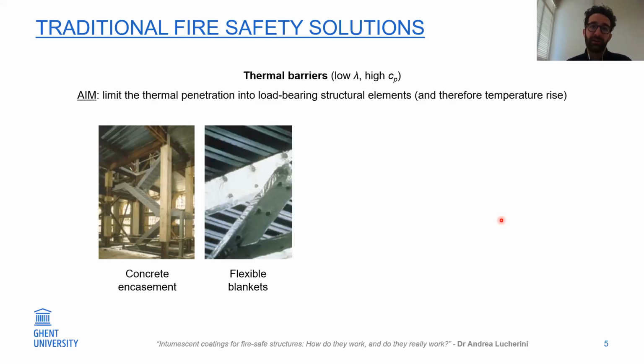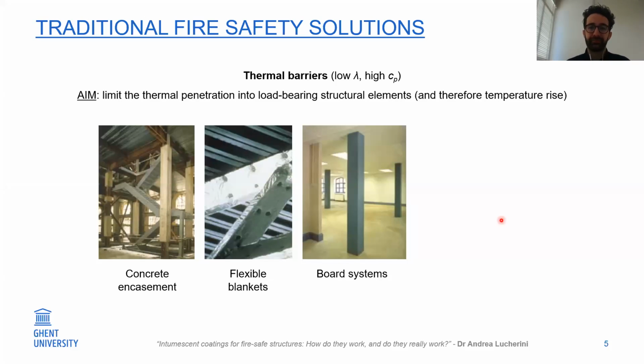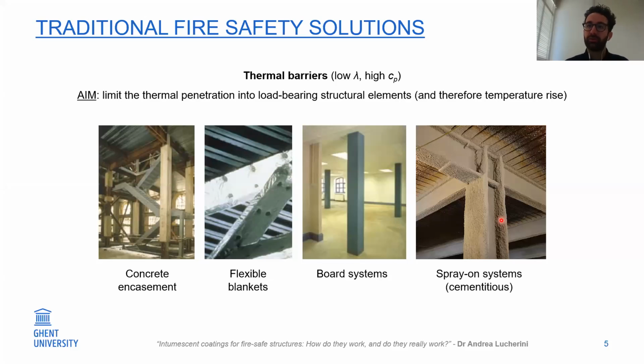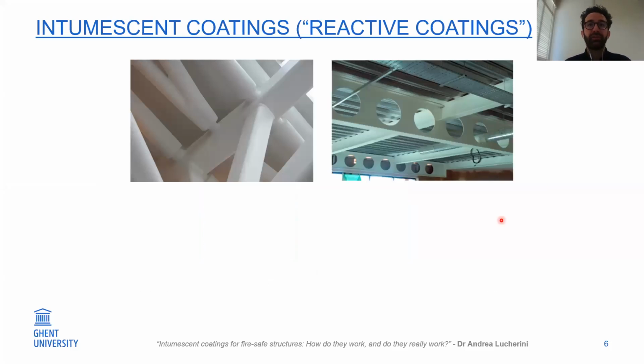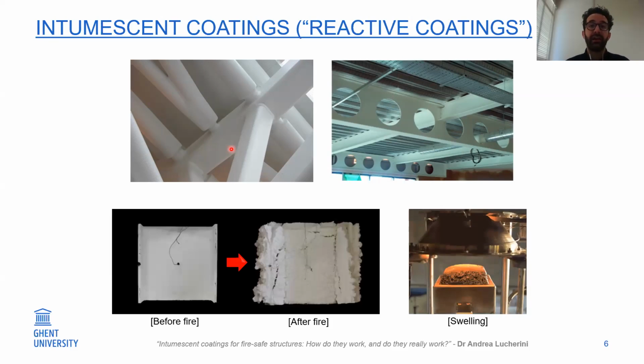Or you can wrap the structure with flexible blankets. Traditionally, you can use board systems, usually based on gypsum plasterboard, a solution that is not very aesthetically pleasant. You can also apply cementitious-based spray-on systems, a solution that you usually see in car parks. And here you can see a newer solution, represented by Intumescent coatings, also known as reactive coatings. As you can see in the slides, it looks like a paint at ambient temperature, but when it's exposed to sufficient heat, it swells and creates a thermal barrier that protects the steel substrate from the fire.